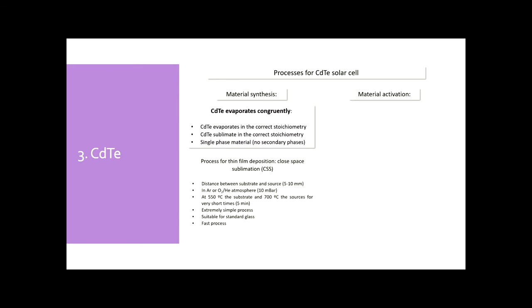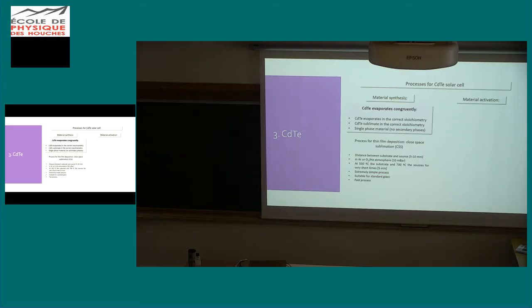So we can apply evaporation, that is the simplest, the beautiful technique. It's very cheap, and this is one of the main advantages of cadmium telluride. The process used in labs and also in industry for producing cadmium telluride is called closed space sublimation. I shall review its characteristics very briefly after a while with some images. Normally you use relatively 550 degrees for the substrate and 700 degrees for evaporating the cadmium telluride source. It's a very fast process, a few minutes, and this is key also for low cost, because it's a very low cost technique.